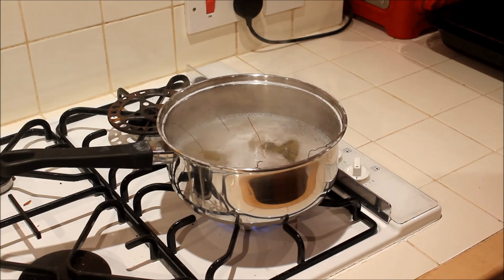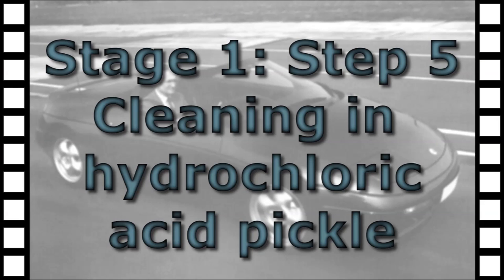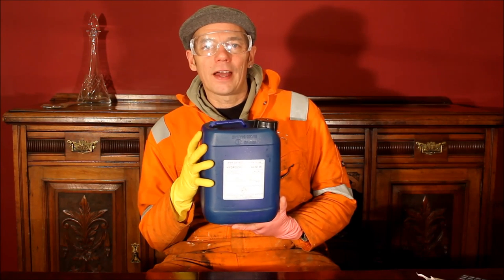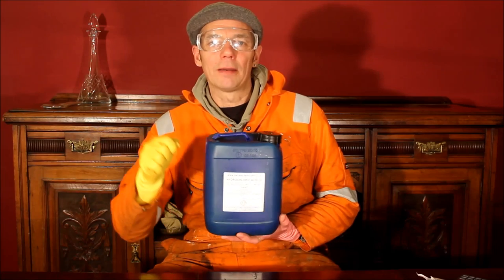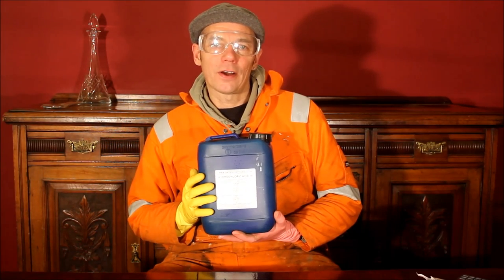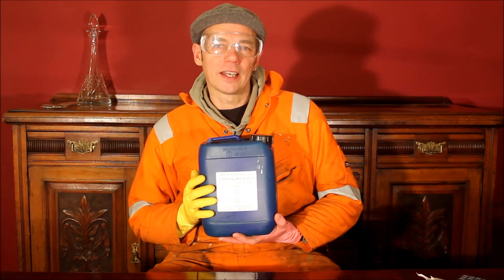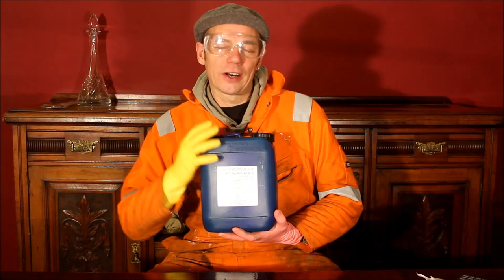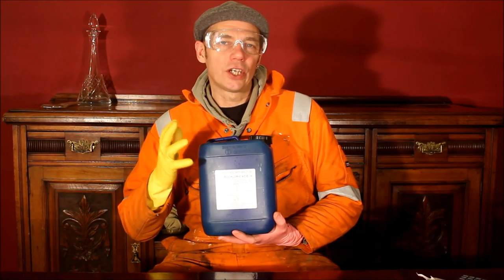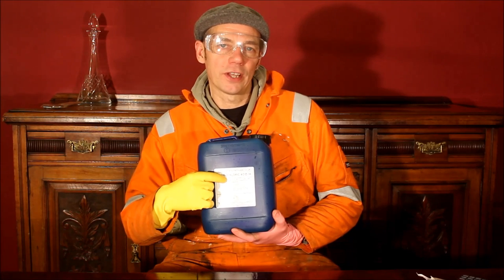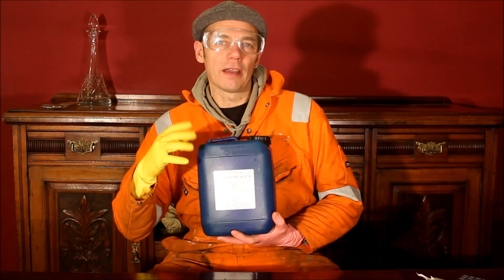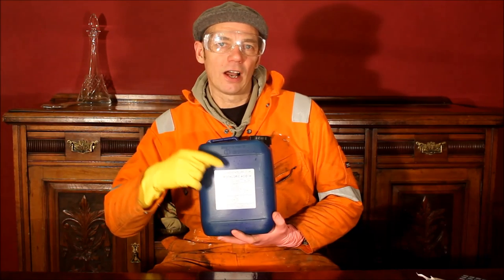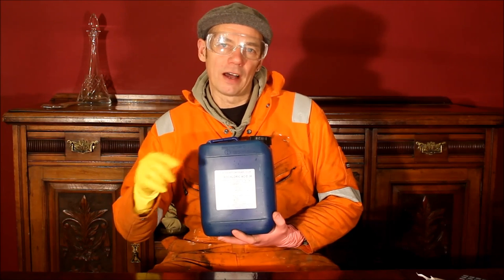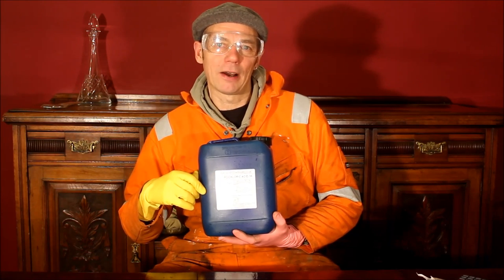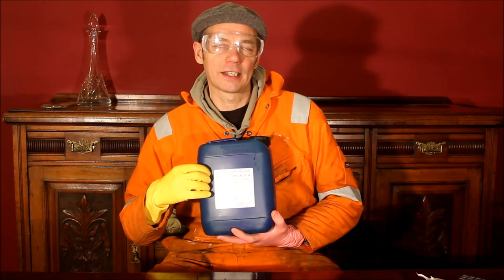Now while they're cleaning in the alkaline bath, let's go and prepare the next stage, which is the acid bath. Now, when the parts have had their alkaline bath, we're going to take them straight out of the hot alkali and plunge them while they're still hot into a bath of 10 to 20% hydrochloric acid in water. Now, hydrochloric acid is also known as muriatic acid if you're buying it. It's usually supplied like this in a concentration of 36% hydrochloric acid in water. So if you buy it like this, basically dilute this down 1-to-1 with water, and that'll give you an 18% solution of hydrochloric acid, which will be about ideal for what we want to do for this steel pickle, the last stage of our cleaning.